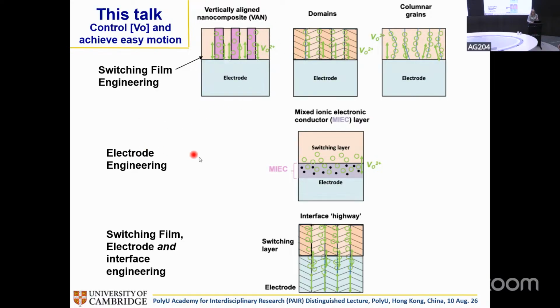If we think about the electrode engineering, we need to do this too. And we need to think about what kind of source and sink of vacancies can we have, because we're going to have to move vacancies out of the switching film into the electrode and back again in an easy way. How do we do that? Well, one way to do that is to form a mixed ionic and electronic conductor. So that could be the whole electrode, or it could just be at the interface where the vacancies move in, but you must have it conducting ionically and electrically, and they can move back. So you have vacancies passing all the way across here easily.